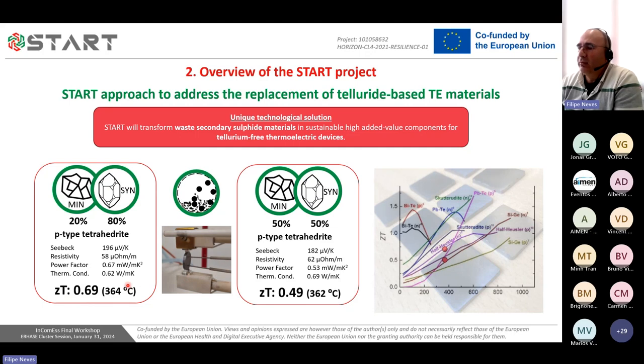In these two cases, it ranges between 0.49 and 0.69. And we can compare here these values with the most common thermoelectrical materials. And in the background of this graphic, you can see here some of the pellets that were already produced and that will be used for assembling the thermoelectrical device.